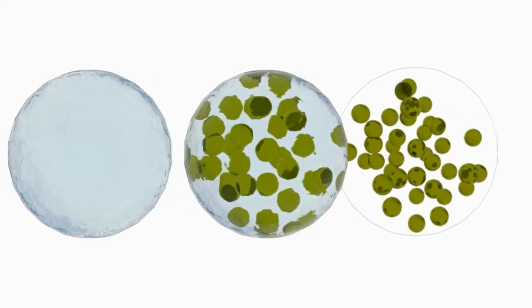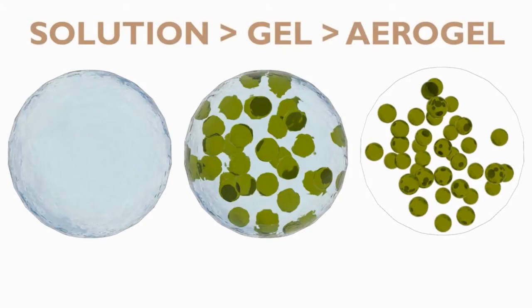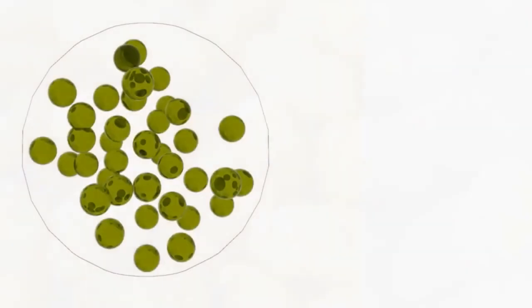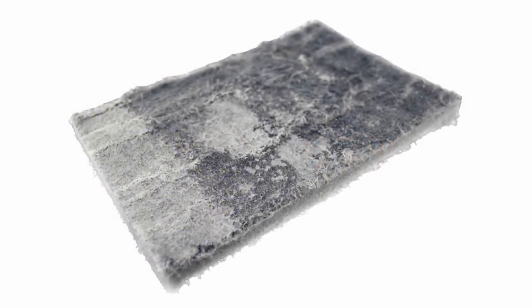Aerogel is a very low density solid that was developed in the 1930s, but has only recently found mainstream uses. Aerogel is a gel in which liquid is replaced by gas without shrinking, via a complex process called supercritical drying. The silica aerogel used in SpaceTherm insulation products is essentially puffed up sand, best described as being to sand what a rice crispy is to rice. The resultant structure is 97% air entrapped into nano sized pores, and while a superb thermal insulator, it is very brittle, limiting its practical applications. SpaceTherm Aerogel takes its aerogel and embeds it into fibrous matte to achieve a combination of excellent thermal performance and robust flexibility.